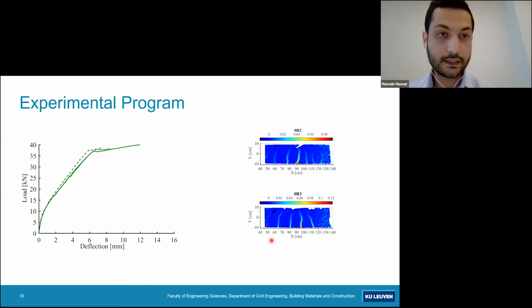I will present first the results of non-corroded beams. I tested 3 beams, and the average bending capacity was around 37 kilonewtons, as shown from the strain field obtained through DIC. Well, I only present 2 of the beams. The beams developed multiple flexural cracks that are closely spaced.